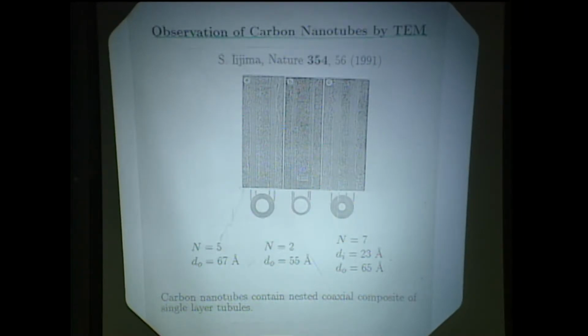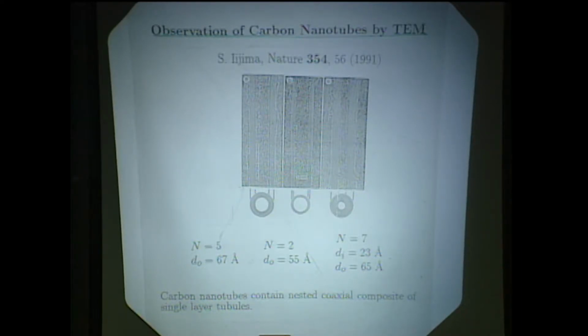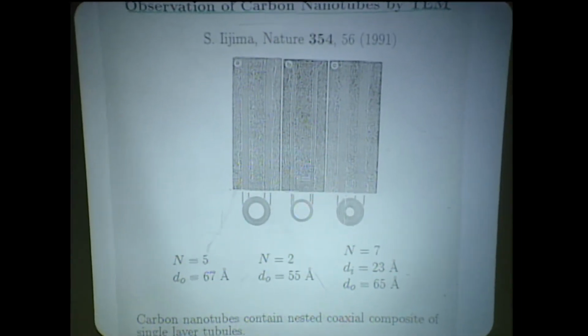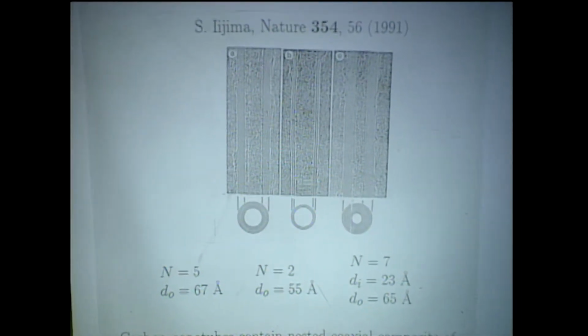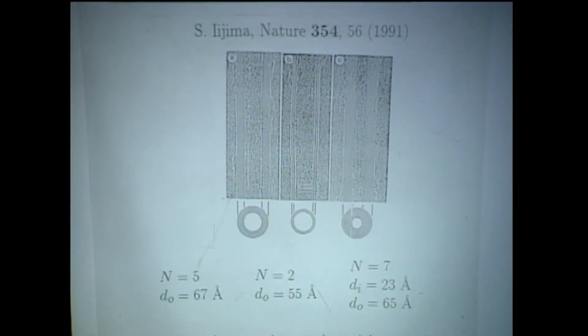Well, very shortly after people started thinking about these tubes, there was a report in the literature, in Nature magazine, and here are some tubes, 67 angstroms, so a little bit less than 7 nanometers in diameter. The inner diameter for this last tube is the smallest, a little over 2 nanometers, so very small tubes, and the length is a micron, so they have a very large aspect ratio, which is very interesting.